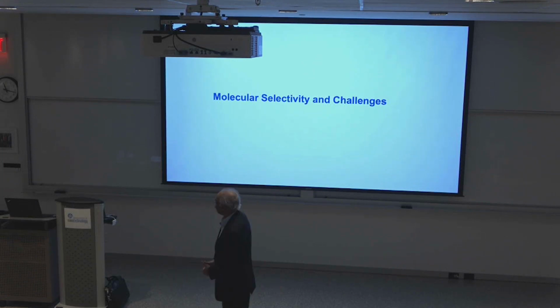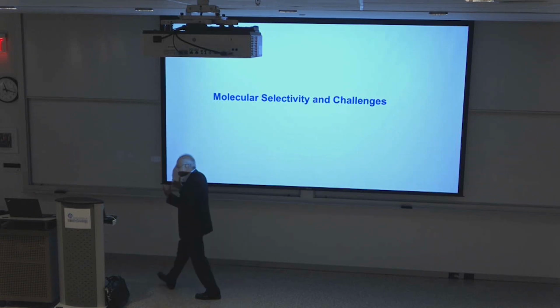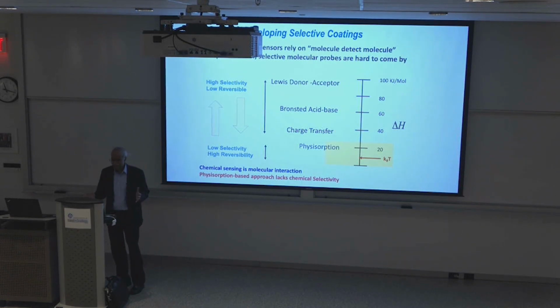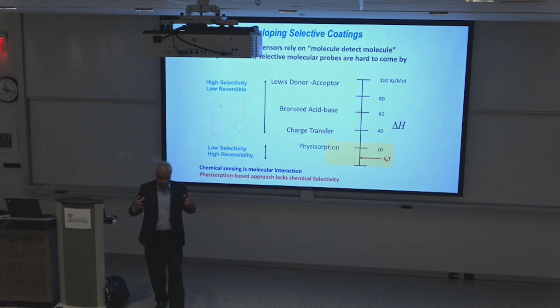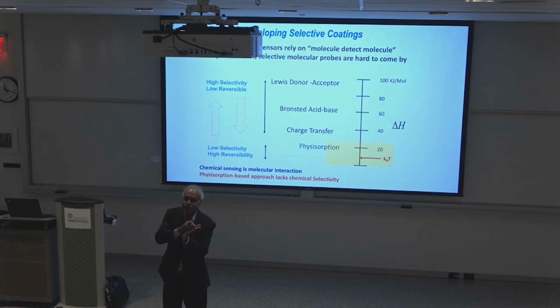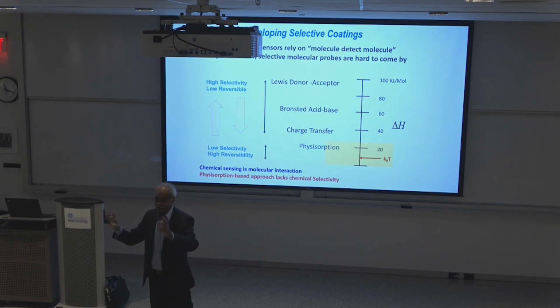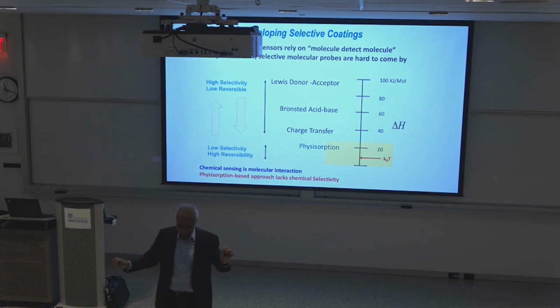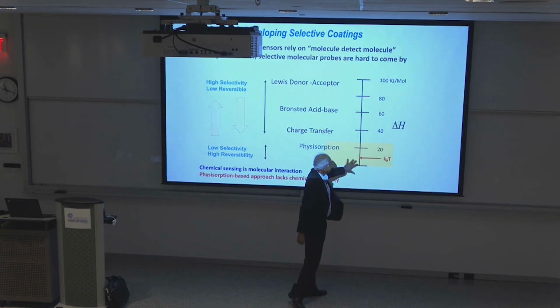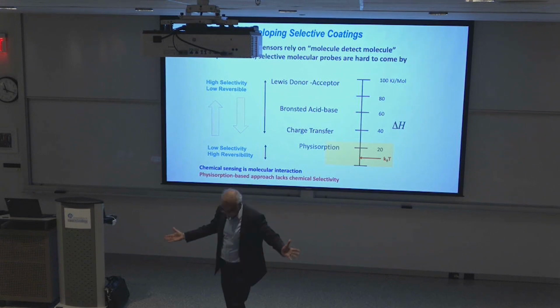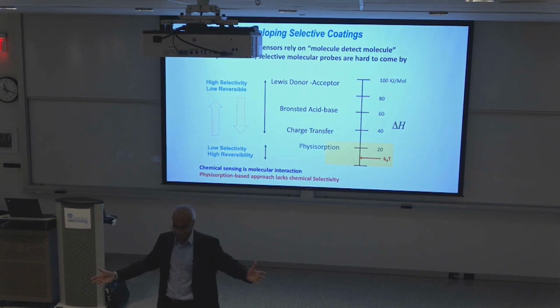So the reason is very simple, because we use the idea of molecule detect molecule: we have a cantilever, we have a receptor molecule, or a polymer or something, that absorbs that molecule. But we want this sensor to be reproducible and regeneratable. That means once the analyte is taken away, the cantilever should come back. You don't want to have a dosimeter where you throw away things like a biosensor. So basically that means you have to use something that can desorb at room temperature, that is kT, thermal energy. Right? So it should be physisorption and van der Waals interaction or hydrogen bonding. That's what we most of the time use.